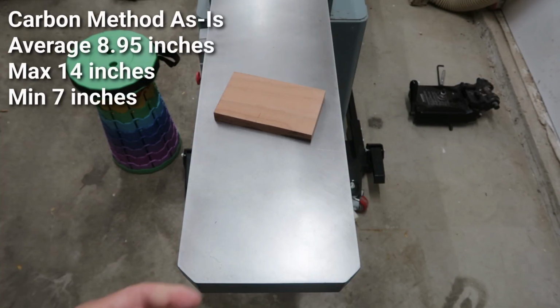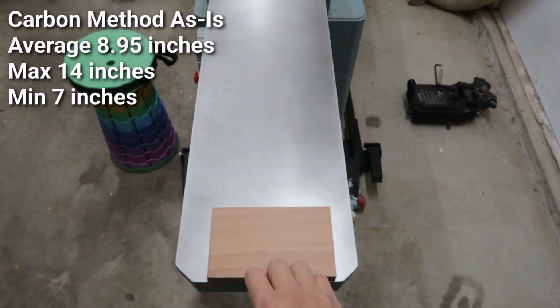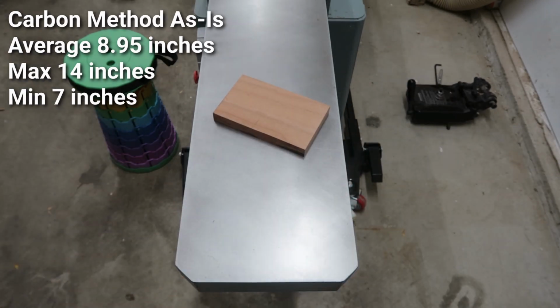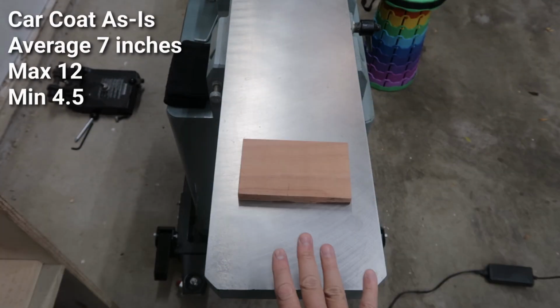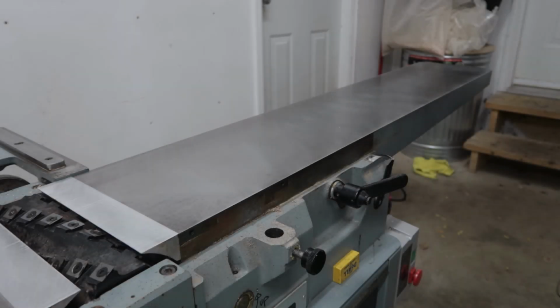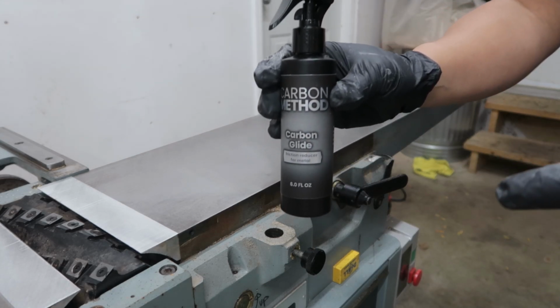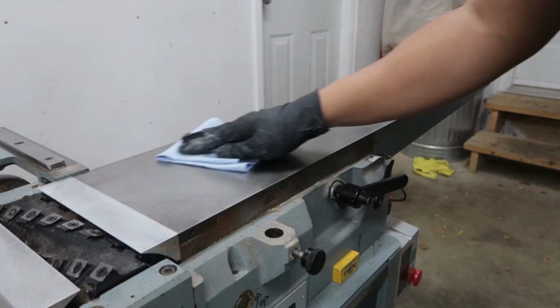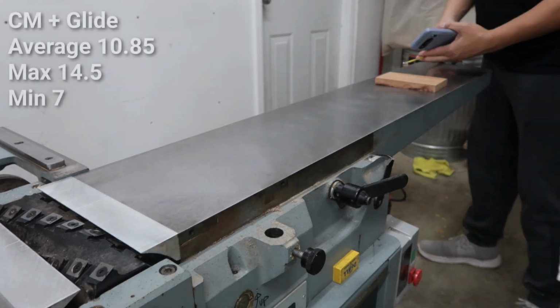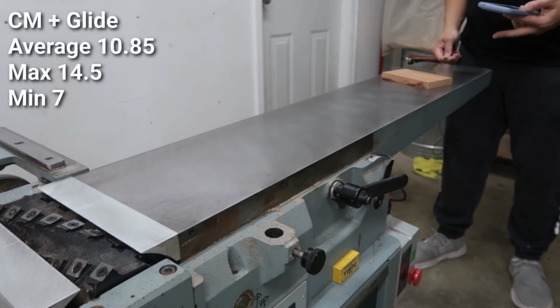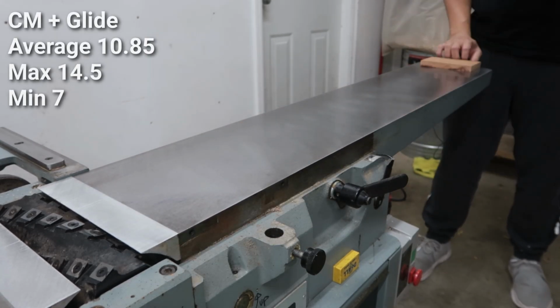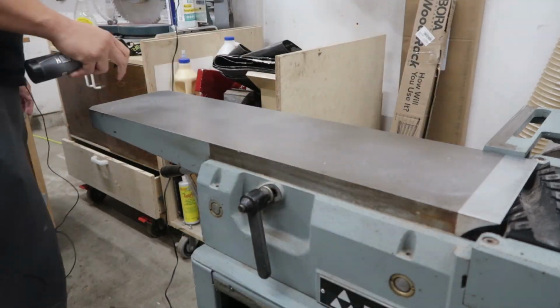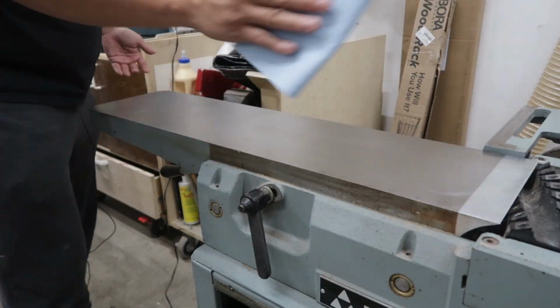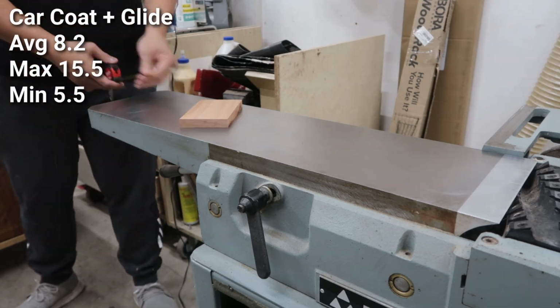The first test is Carbon Method side as is. Second set, car coat as is. The reason why I say as is is because the Carbon Method kit comes with a spray called Carbon Glide. It will make the surface smoother. We're going to apply it on the Carbon Method side and run the test again. Of course, we'll spray the glide on the car coat side as well and run the test again.